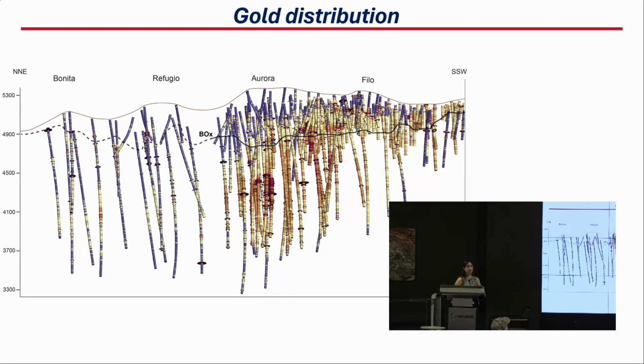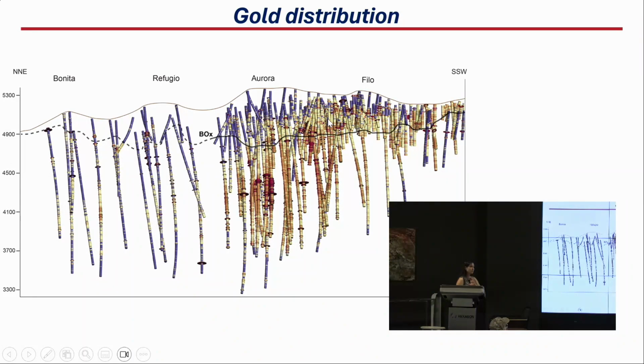Now if we see the gold distribution, in this region, throughout assays, we also have very high grades of gold, but this region is completely destroyed, so it was really hard to log and to determine how the gold was actually there. But we know so far that in this region, gold is present as native gold. It has been reported. I mainly found gold in pyrite, gold in enargite, and gold in copper sulfide. It's reported from the porphyry region.